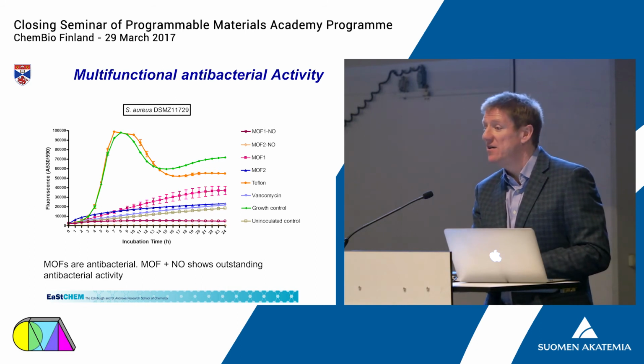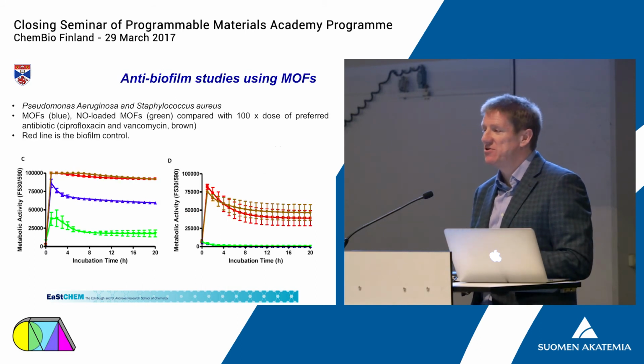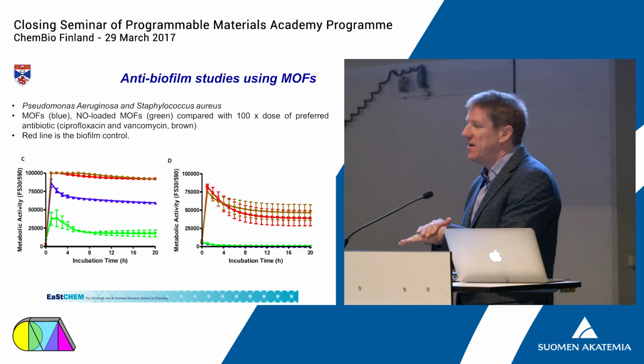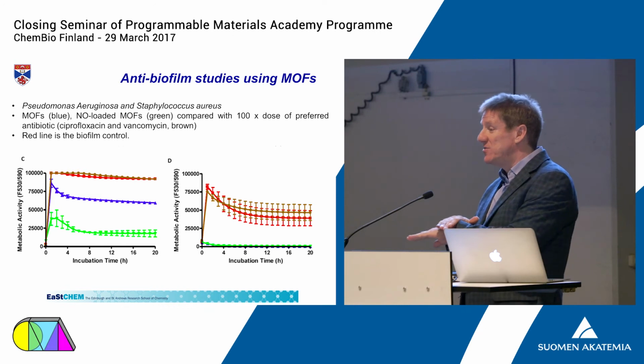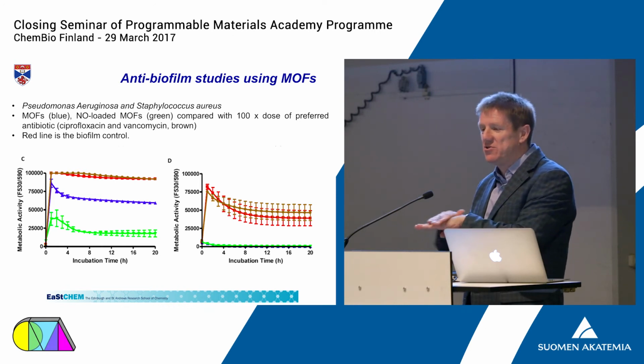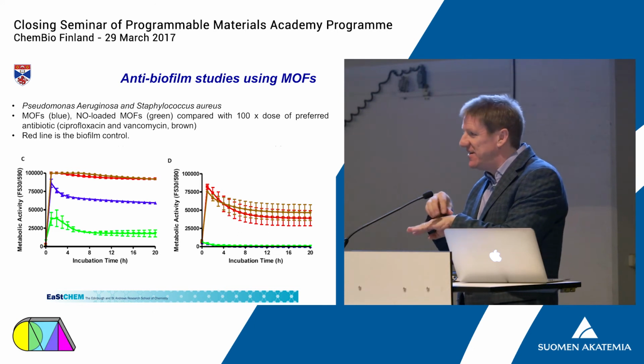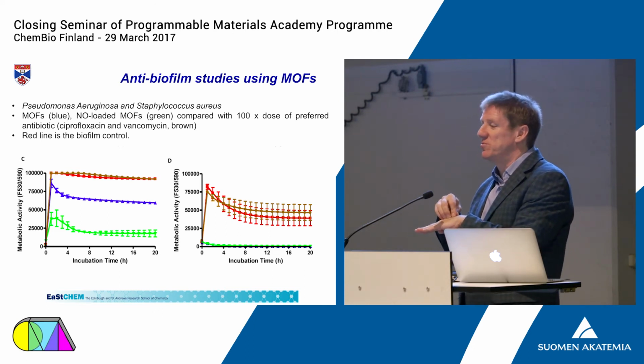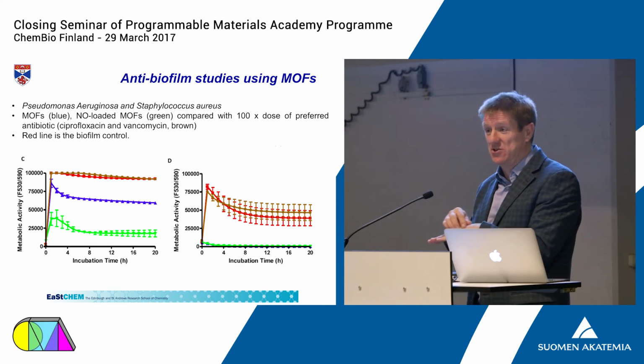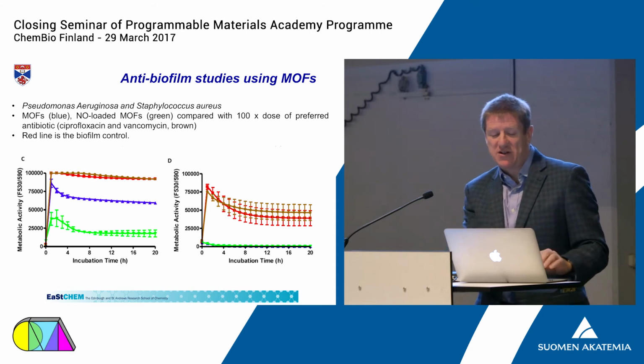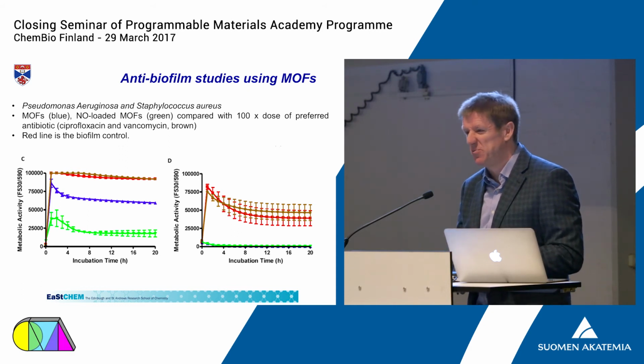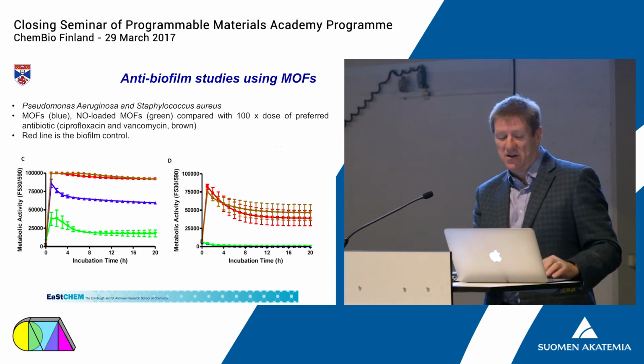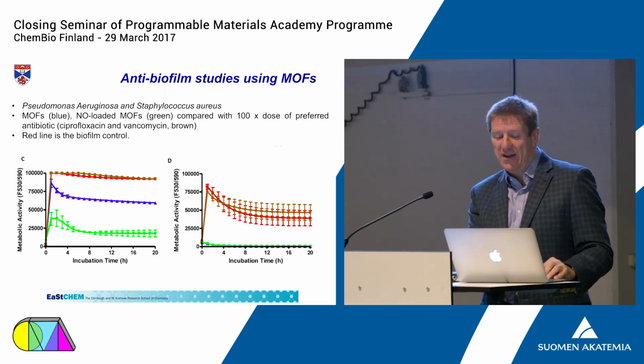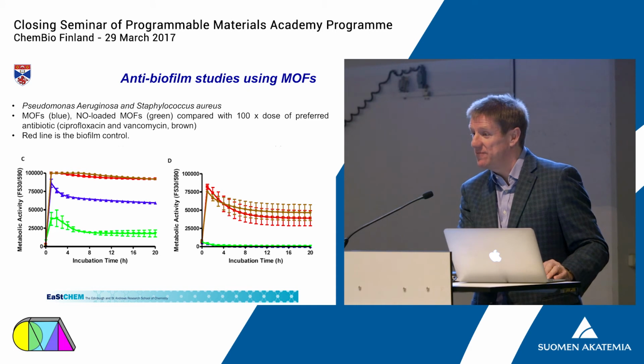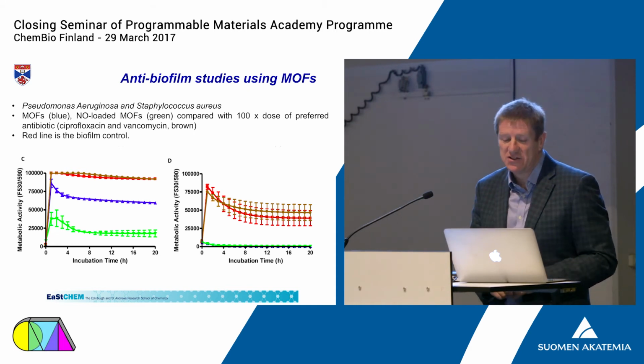And much more interestingly is when we start to expose these things to biofilms. Biofilms are when the bacteria, and they cause a lot of trouble, start to form like a polymer, which the bacteria start to live in. And they can cause real serious problems, because then they get really difficult to kill, to disrupt. Whereas nitric oxide, probably because it's really small and gets in these places really quite well, is really, really good at killing lots of different types of biofilms, in situations where the antibiotic of choice doesn't do anything. So it's a real serious issue.